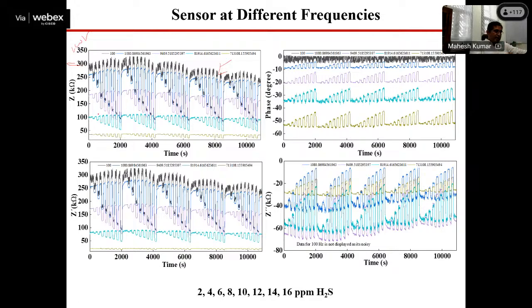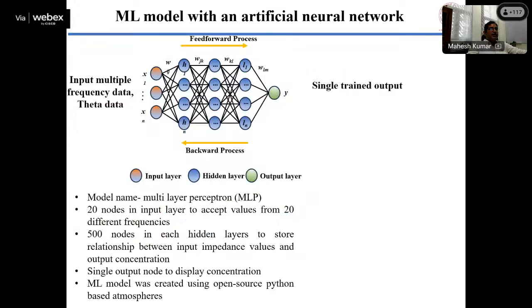But if we go higher, around 10K, our baseline is stable. So if you measure at 10K frequency, we are getting stable data here. And the phase is stable, even at lower frequency it is stable. This gives a more accurate value than the resistance. So all of these parameters we have measured, and then we have used them in machine learning.